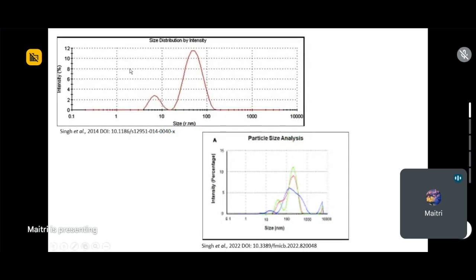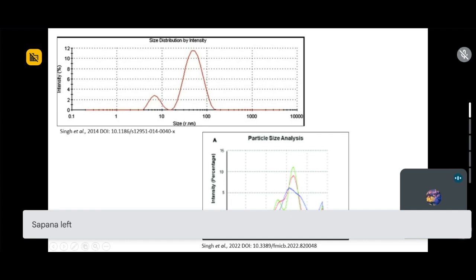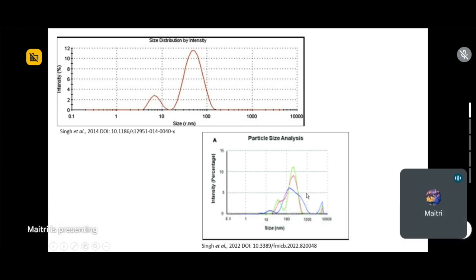And this is how an actual DLS graph looks like. So see, you get a small peak, you get a large peak. This large peak means more nanoparticles of this size range, less nanoparticles of this range, and the nanoparticle size range over here will be between 10 to 100 nanometers, and mostly it will be around 50 nanometers or something. And the intensity is very high, meaning the area under the peak and the amount of AgNPs formed is very nice and very high. And then this is also telling how different conditions can affect the particle size, like different pH conditions and something.